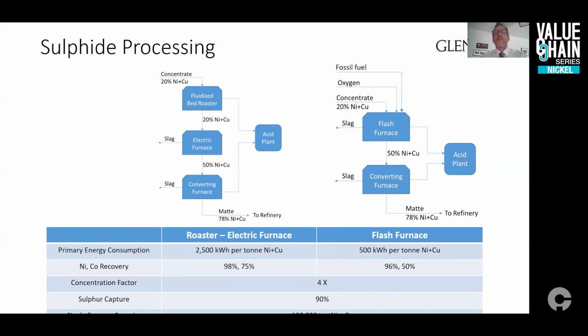The main differentiators between these two processes are electrical energy consumption and metal recovery, and they trade each other off. Energy consumption in flash smelting represents the energy required to produce the bulk oxygen, which is not insignificant. Although cobalt is not present typically in high concentrations, historically the price of cobalt has been up to 10 times the nickel price, so it's an important economic factor of the process.